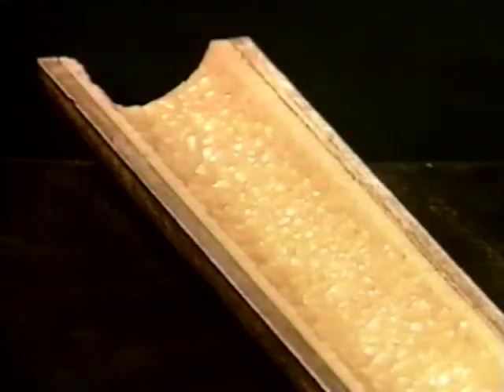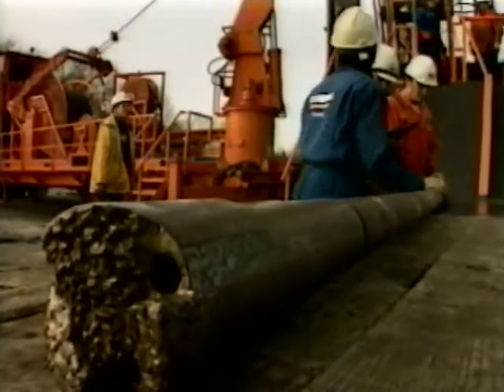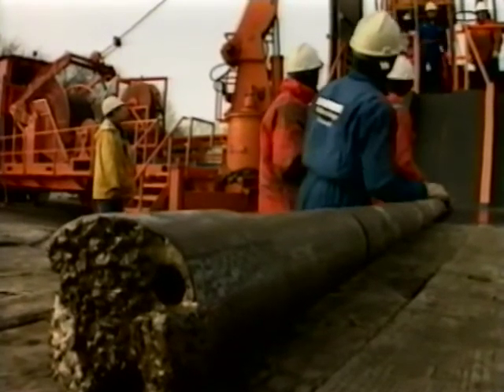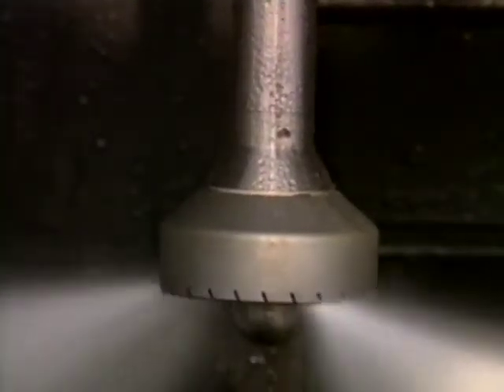One of our clients used the sterling bead system to remove aragonite, a form of calcium carbonate. All other systems had failed completely, and 12 tungsten carbide mills were destroyed in 4 days. So what happened when they tried using the sterling bead system? It worked. It cleaned 425 feet of tubing at between 30 and 90 feet per hour.